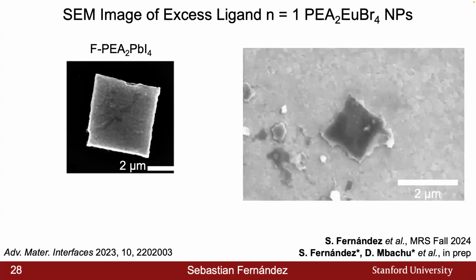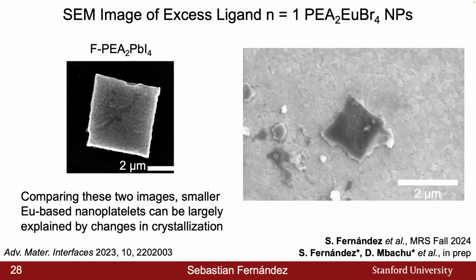Of course, we're missing some additional information, such as EDS, which is currently still in play. But in general, what I want to say here is that there are some size differences here, which are largely attributed to the changes in crystallization from the material. But in general, we're seeing a very similar shape and along a very similar lateral size, which is really indicative that we are forming what we think we are forming.